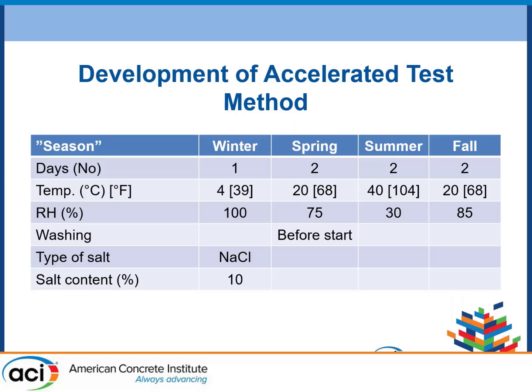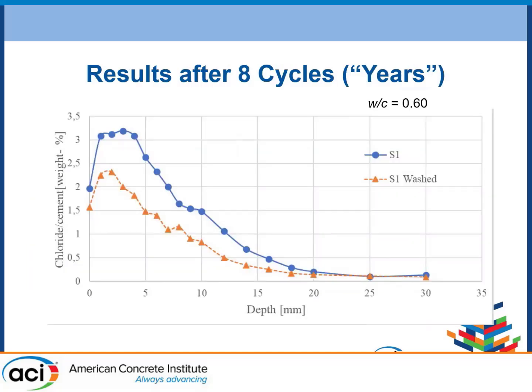And then we developed an accelerated test method. In our case now we make 1 year in 1 week. So we have 1 day of winter, and then 2 days of spring, 2 days of summer, and 2 days of fall. And you see that the temperature varies, and also the relative humidity. When we are looking at the effect of cleaning, we clean before the spring, and you see that we have quite a high concentration of salt. And here, after 8 cycles or years, you can see there is a rather large difference between washed and unwashed samples for water-cement ratio 0.6.